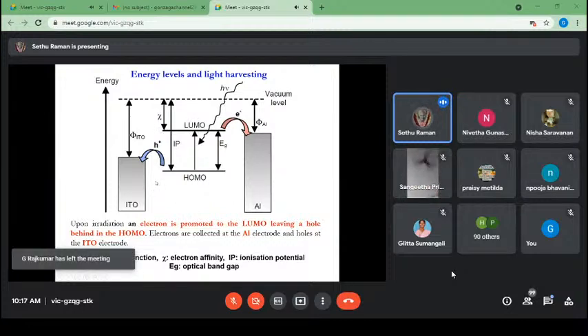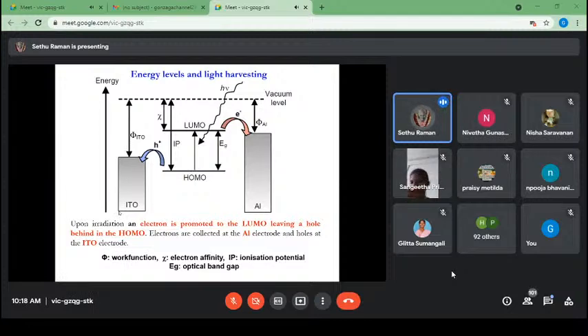So fabricated here, you see how the HOMO level matches with the ITO work function, and how the LUMO level matches with the work function of the aluminum electrode. This is the aluminum electrode work function, and this is the ITO electrode work function. Light is incident on the material, light absorption takes place, and an exciton is generated. Electrons are excited to the LUMO level and travel towards the aluminum electrode, and holes are created and travel towards the ITO anode. So a circuit and current is generated.